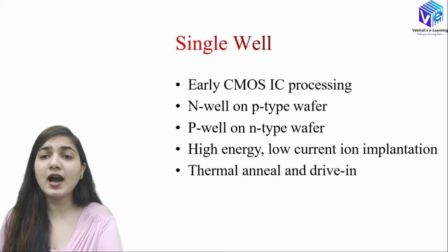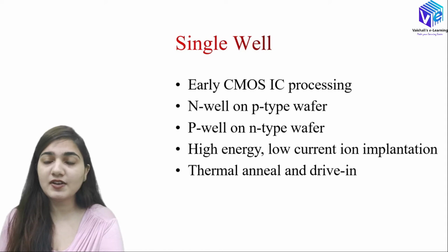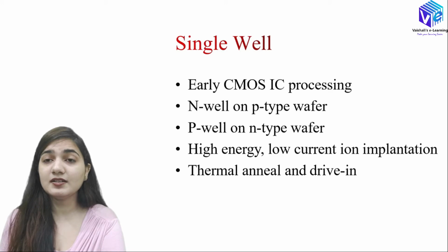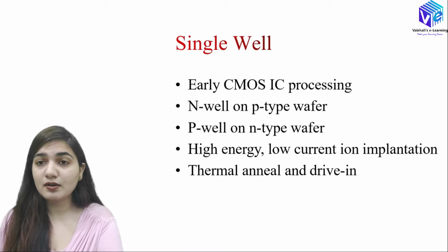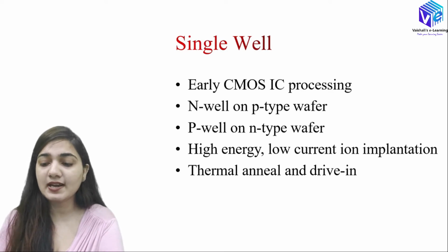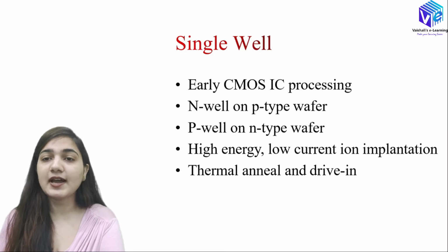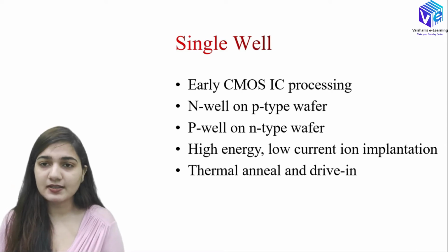So when I was using high energy ion implantation process, high energy ion particles are bombarded on the surface. So when high energy ions are bombarded on the surface, atoms may get displaced and the single crystal structure would be degraded. I want it back. For that I will be using the thermal anneal and the drive-in process. In the drive-in process we are giving high temperature so that the ions will penetrate deeper inside the substrate. So I hope you understood the single well process.